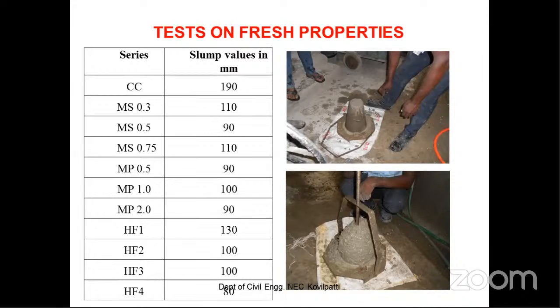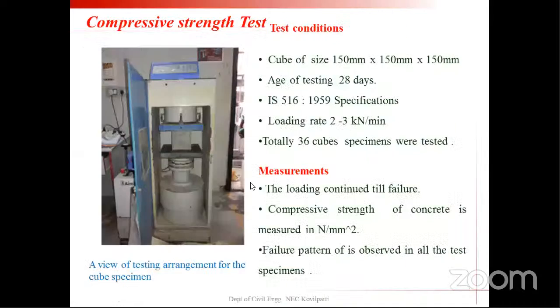And also I have added silica fume as well as supplementary cementitious material like fly ash. The nature of fly ash is spherical, so spherical particles will always improve the workability. If particles are very spherical in nature, there is less frictional resistance, and that will obviously improve the workability properties. And silica fume is also finely dispersed particles. So all these things help to improve the slump properties of the concrete.